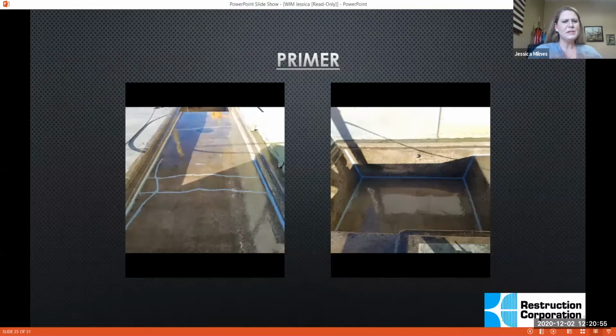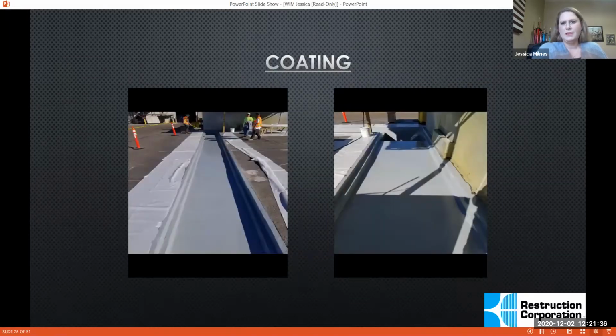So what you see here is it looks wet. So this is the primer. The primer we used on this one was actually clear, but you can see really well that we chase those cracks. So we grout out the crack in order to give us something to bond to. And what we also want to do is get to good concrete that doesn't have acid in it, because we don't want the acid coming up through the concrete. Otherwise, it's going to bubble our repair materials. We don't want the acid going down. So we have to get this to the point where there isn't acid left in the concrete. So we fill in the cracks and prime it. And then this is the coating.